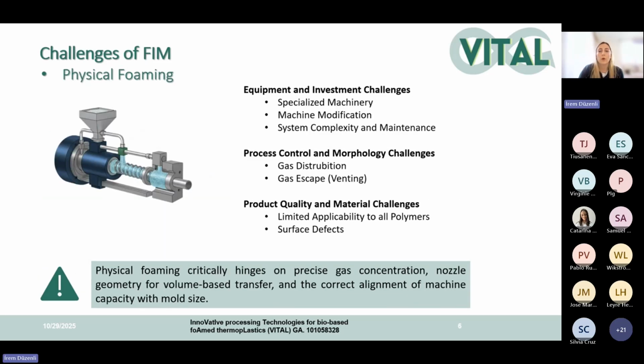Now for physical foaming, which we already talked about. In this process, we inject a gas like nitrogen or carbon dioxide, and it also has some challenges. It's different from chemical foaming because you need equipment. It has investment challenges because you need specialized machinery, and you cannot directly apply it to the injection machine. You need some modification of the machine, and the system is more complex.